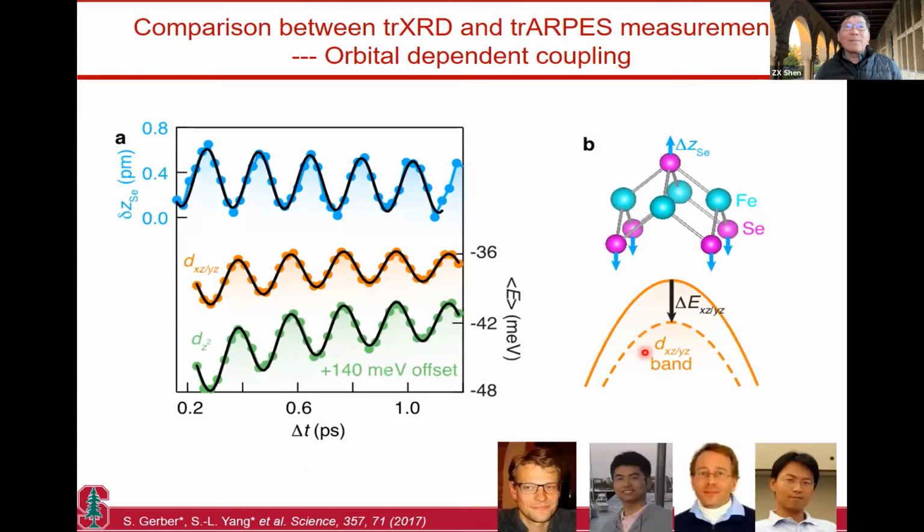And if you now put these two together, the upper one is the vibration of atoms up and down. And please look at the scale. It's very, very small. It's from here to here, 0.8 picometer. It's far less than an angstrom. This constraint, as you will see later: we know that a typical material has a lattice constant of about a couple angstroms.